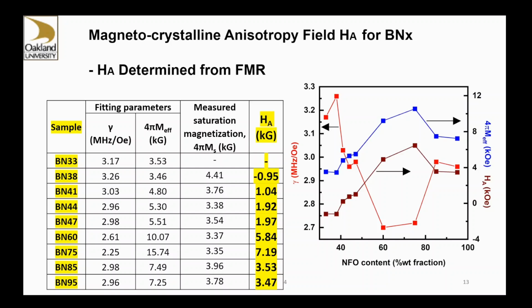So the way it looks, all the hexagonal ferrite platelets have the C-axis in plane. That's the reason for a very large in-plane anisotropy field. It's pretty good. It's as high as 7 kilo-oersted for some of these composites.